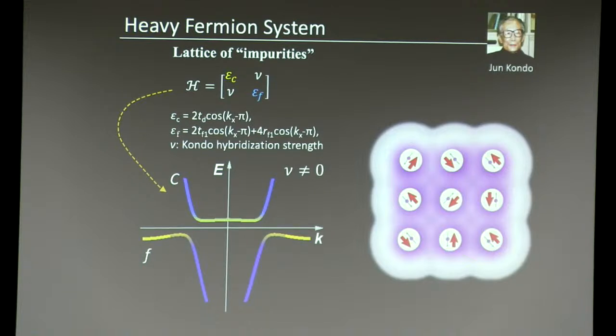As you lower temperature, you get into the heavy fermion ground state, where the two bands have hybridized and the local moments have now been screened by the conduction electrons. If you look from far away, you won't even know that this system has local moments—the local moment physics is now really gone. Now, depending upon where your Fermi energy is, if it lies in this gap, you have an insulator. So there are heavy fermion insulators.